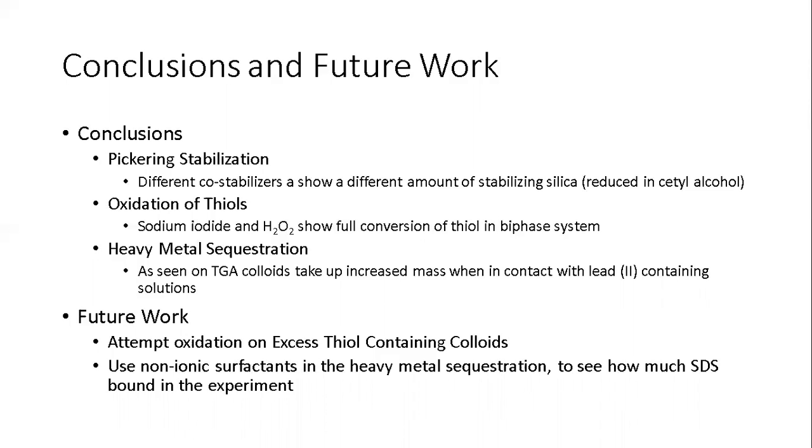However, we didn't do this on a particle basis yet, so the next step is to take the particles we've made that have excess thiol and, of course, oxidize them and see what the size increase is. For this, we're planning on starting with 50% excess thiol and working our way back to see if there's a different size increase for each amount of thiol.